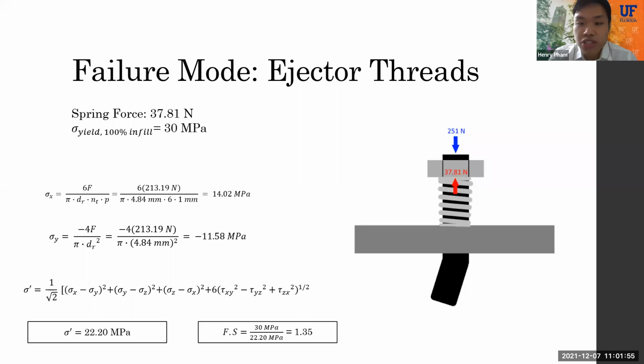Using the yield strength of the PET-G at 100% infill, as given by our manufacturer, we found that the overall factor of safety for the 3D printed part was 1.35. Again, this is assuming that the motor produces its maximum force and that actual operations will produce a much lower stress.